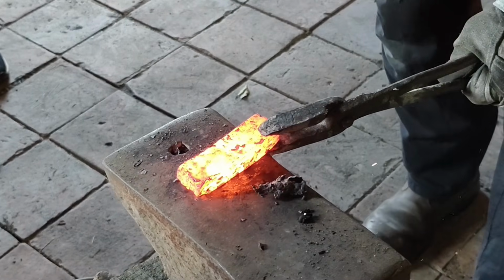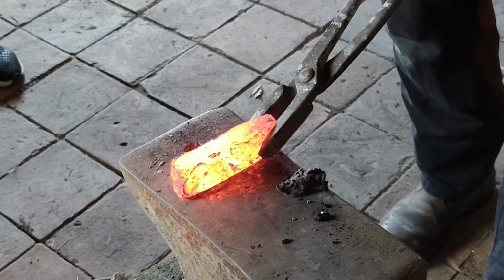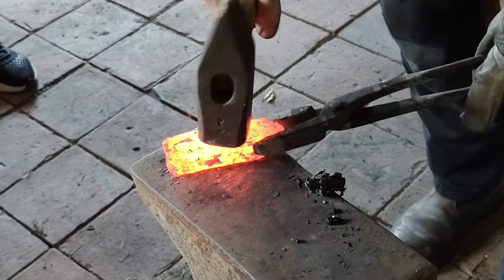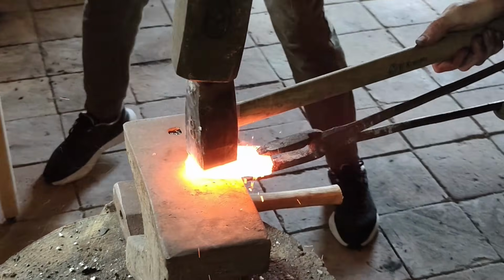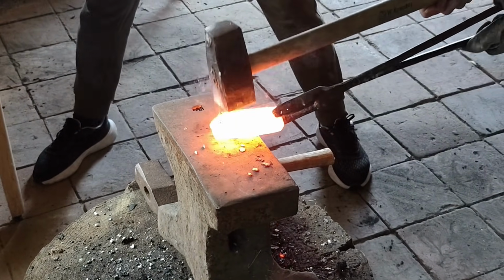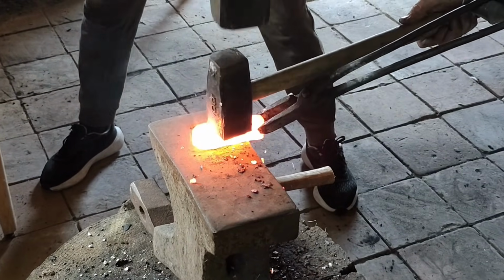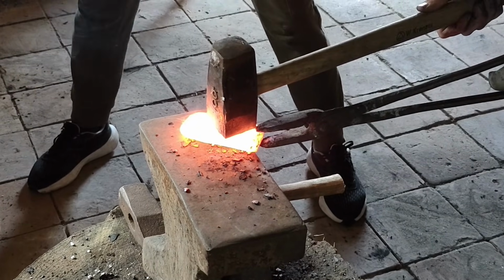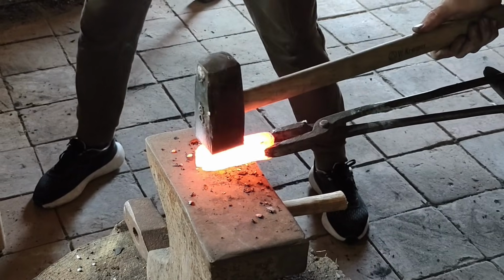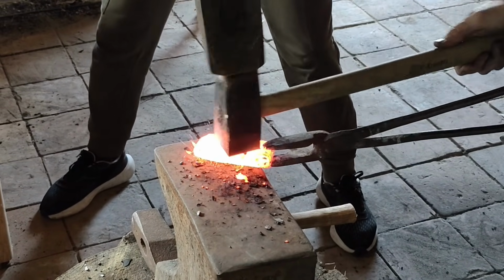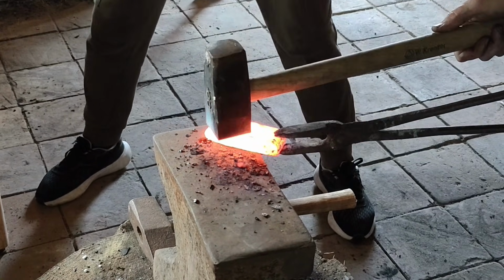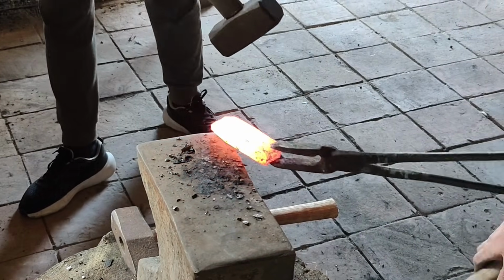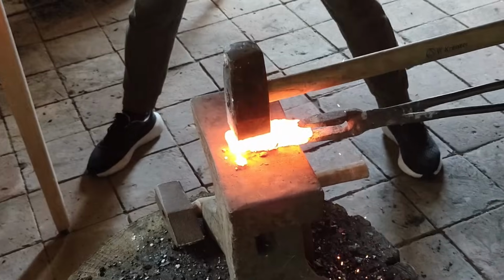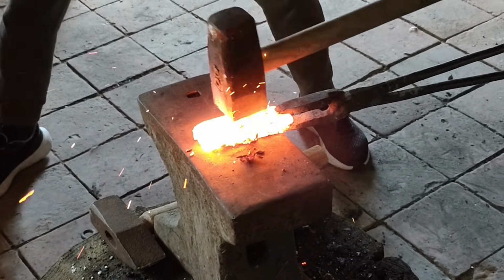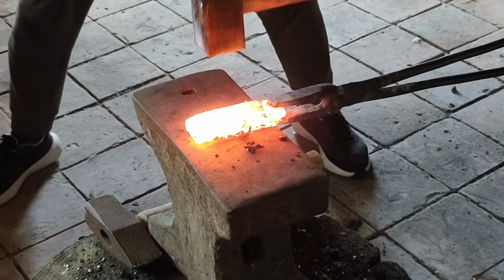Early medieval steels, in particular low to medium carbon steel, need quite fast cooling rates in order to properly harden, and making the middle portion of the blade thin is the solution to this particular problem. Therefore, applying a fuller in a sword is a marvelous innovation of the early medieval smith, and shows the know-how to effectively incorporate different types of steel into sword design, but also shows that knowledge of tempering and advanced heat treatment techniques were known. Actually, applying a fuller into a sword design only makes real sense if carbon steels have been applied into the body of the blade, with remelting of bloomery iron via the hearth refinement technique providing the best quality of high carbon steel.